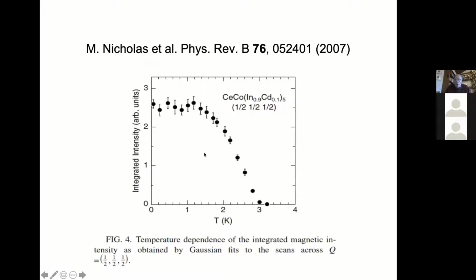But Michael Nicklas and his co-workers discovered that if you look at one of these alloys, in the magnetically ordered regime of these materials, this is the development of essentially the order parameter on cooling, and this is where TC happens in this material. And the magnetic order stops developing. In other words, superconductivity cuts off further development of the order parameter there, which to me is highly reminiscent of exactly what we were just seeing in the A15 materials in the previous slides.